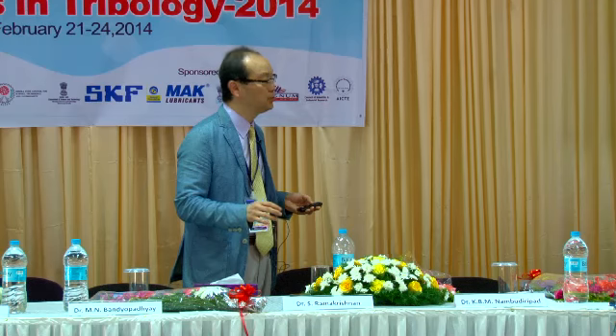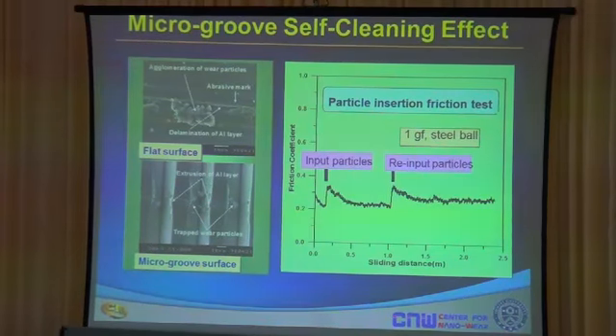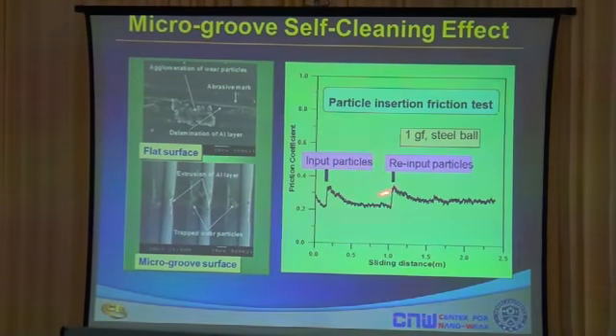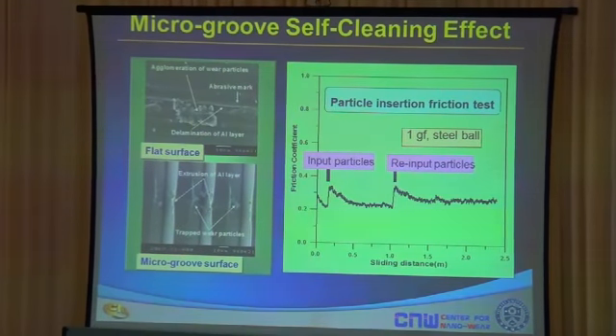This is the friction coefficient versus sliding distance. And at this point, we input the particles artificially, and the friction shoots up. But because of the grooves, it is able to self-clean the interface and lower the friction. Now we input the particles again, and the friction coefficient shoots up again. And then it is able to, again, eliminate the particles and reduce the friction automatically. So we have to use this kind of textured surface as much as we can in many mechanical systems to be able to reduce the effect of plowing action by the wear debris being created at the interface.